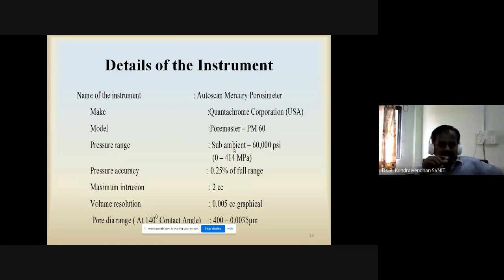So these are the details of the instrument. The name of the instrument is AutoScan Mercury Porosimetry. This is Quantachrome. There are a number of manufacturers and brands available, and among these, Quantachrome is very popular. The model is called PoreMaster PM60. The pressure range is from subambient up to 60,000 psi, or 414 megapascal in Pascal. The pressure accuracy is 0.25% of the full range. The maximum intrusion is 2 cubic centimeter, the volume resolution is 0.005 cc, and the pore diameter range is 400 to 0.0035 micrometer.